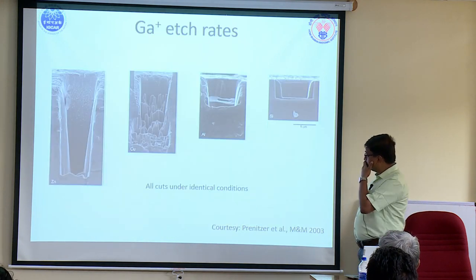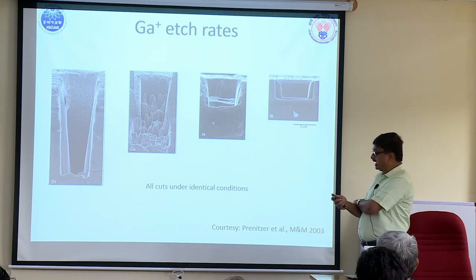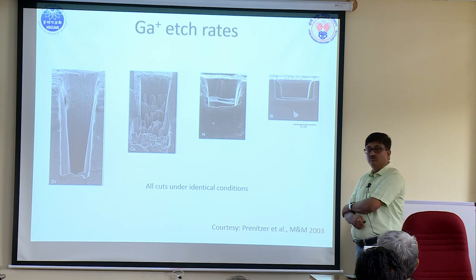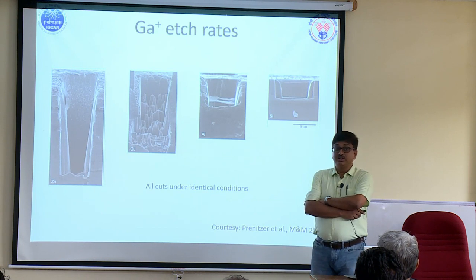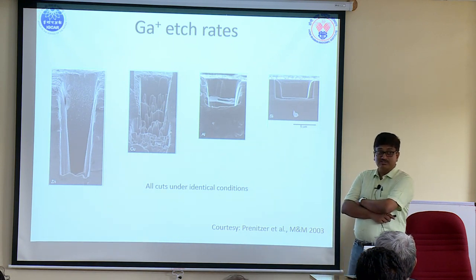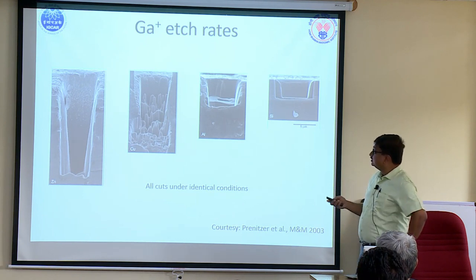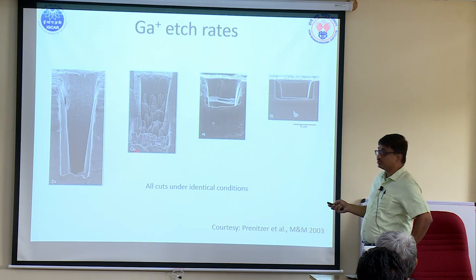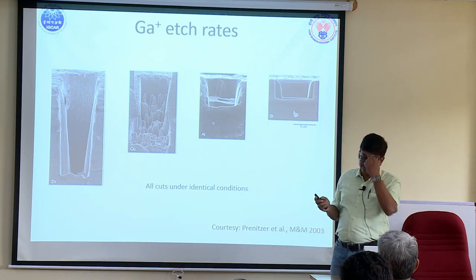What I am trying to show you here is that we are using the same kind of conditions, and we have 3 metals and a silicon. The technique was basically developed for silicon and is not so good for metals. You need to be really skillful to use it for metals, and I am going to tell you why. Silicon, of course, is no problem; it is used in the silicon industry left and right for all quality control and stuff like that. This is zinc, this is copper, if you can read from the back, this is aluminum and this is silicon.